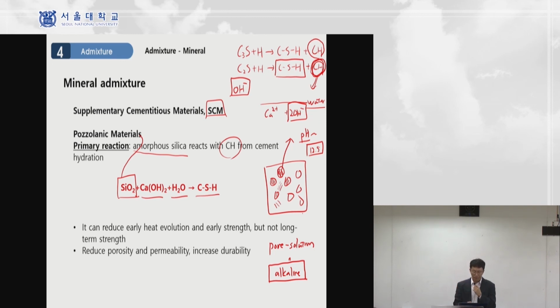Okay? So this calcium hydroxide can come from the pore solution in the pores of concrete. So it is a very interesting phenomenon that this amorphous silica in fly ash or in silica fume will react with this calcium ion and OH- hydroxide and water to produce this calcium silicate hydrate.